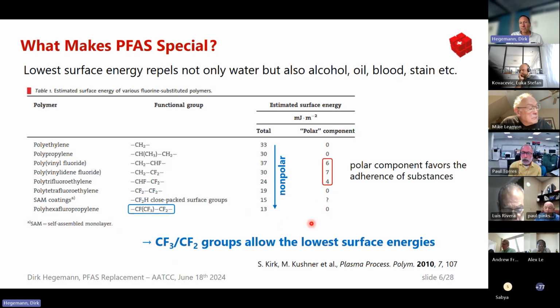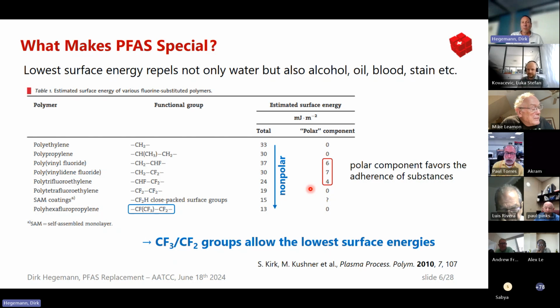The amount of fluorine cannot simply be reduced, at least not by introducing some hydrocarbons, because then you might also get a polar component, and they are by far not as good. So by far the best treatment you get is a mixture of CF3 and CF2 groups, and that is what PFAS is all about.